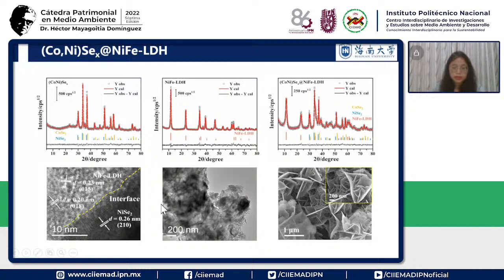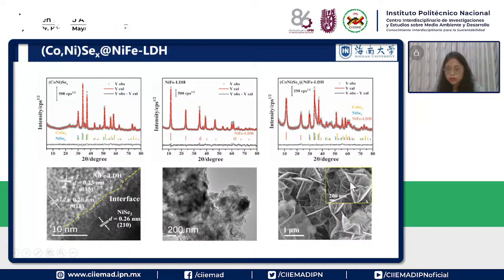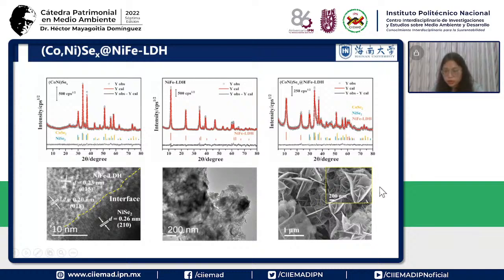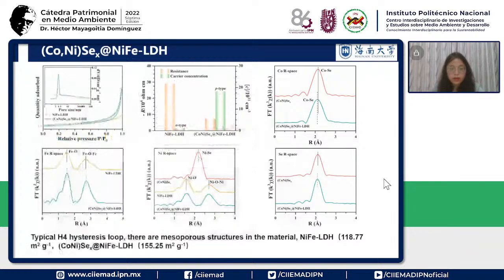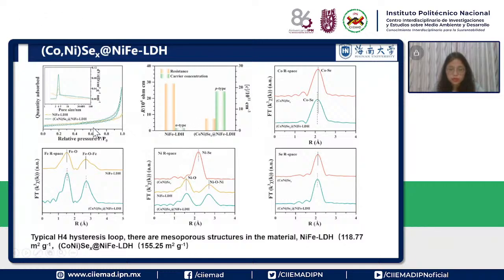This region is maybe in another region, and this material shows a flower-like microsphere, with LDH on the surface. The LDH shows a different morphology: one is sheet-like, and the other is wire-like on the surface of the selenide. Then we continued to find information on the pore structure and also the conductivity. They show the typical H4 hysteresis loop, which means there are mesoporous structures in the material.